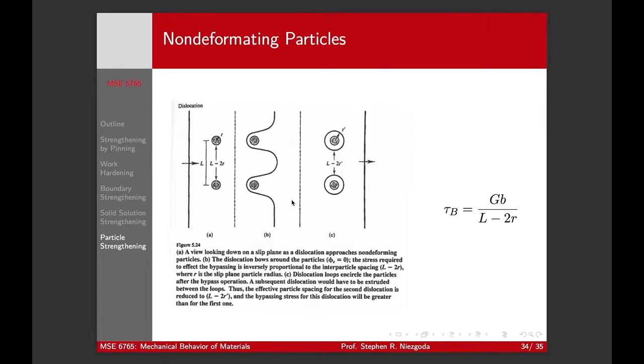So you're left with a dislocation loop around the obstacle, right? Where now this whole region has slipped, and this little region in here has not. And this dislocation, this interface, right, now continues to move on. So sometimes it's easier to think of dislocations as boundaries rather than as a discrete defect kind of thing.